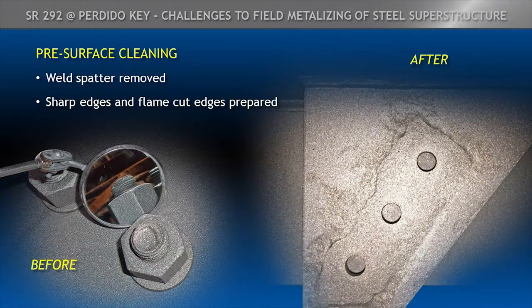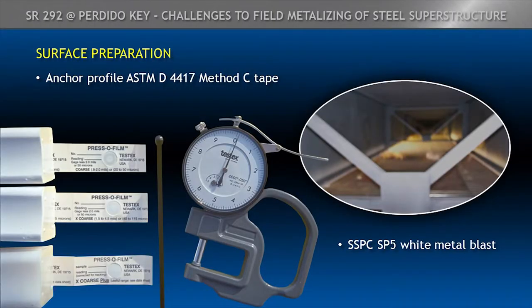Pre-surface cleaning, we removed weld spatter, sharp edges, and things like that. This is just a picture of the surface preparation before and then after. And that was a pretty good SP5 blast that we could put the metalizing over top of. Anchor profile, we checked with replica tape, which is one of the most common methods, ASTM D4417 method C, and we actually required 5 tests per 100 square feet. Because of the mechanical bond of the metalizing, the one thing you really have to know is that you're getting good adhesion to the steel, and by making sure you have the right surface profile, it can eliminate problems.